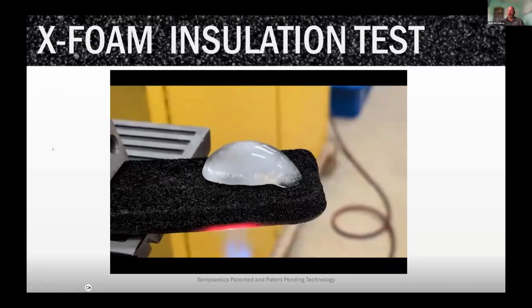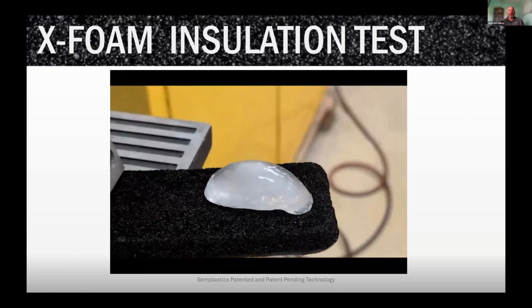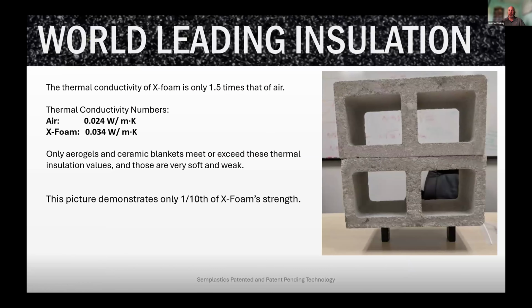So the thermal conductivity of this material was a little bit surprising to us and remarkable. We found with official thermal conductivity testing that it is only about 1.5 times as thermally conductive as air. So if you had nothing there in air, this would only let through 1.5 times as much heat as that. Only aerogels and ceramic blankets can meet or exceed that kind of thermal insulation value.